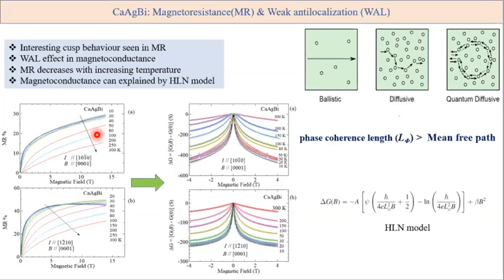For our case, we may have some small remnant magnetic field, but that doesn't affect it here because this is completely non-magnetic. Before starting a measurement, we generally oscillate the magnetic field to kill any remnants, but you may still have some remnant field. That may be very low, but in this case we did not measure the remanence field.